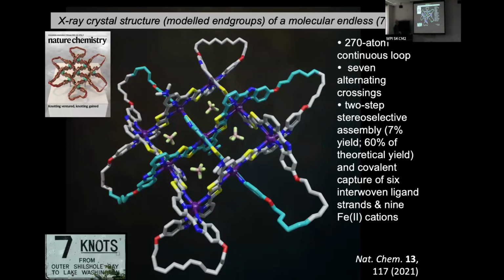How do we know that? Well, this is the X-ray crystal structure of that grid with the end groups modeled on here to form the heptafoil knot. And you can see that the reason that it forms are indeed these BF4 groups that are found in all 4 of these cavities and stabilize the formation of that 3x3 interwoven grid. So we didn't design that at the start. That was a problem that we had to solve, but now we understand that design element.